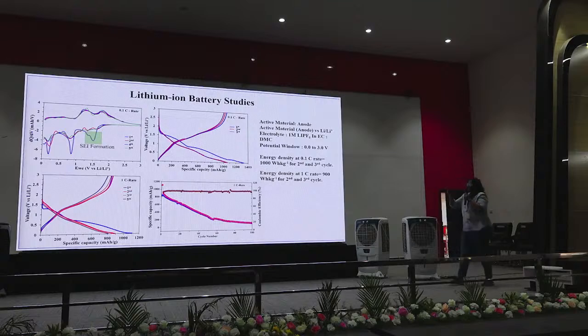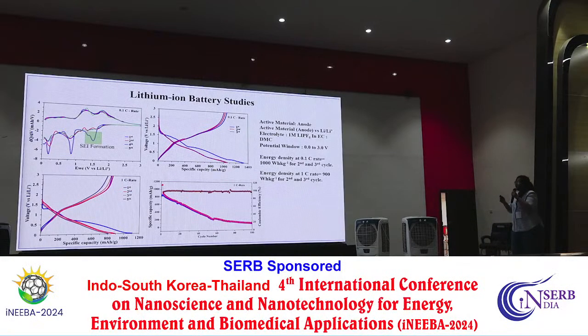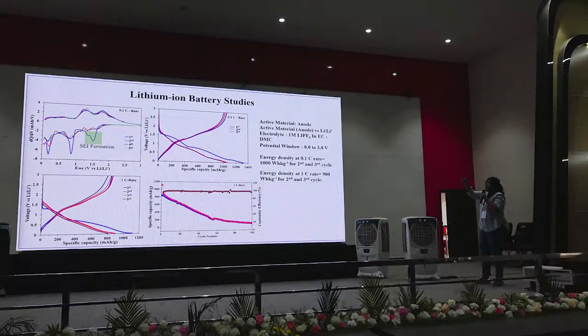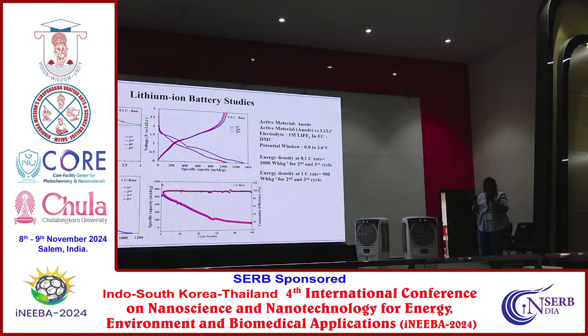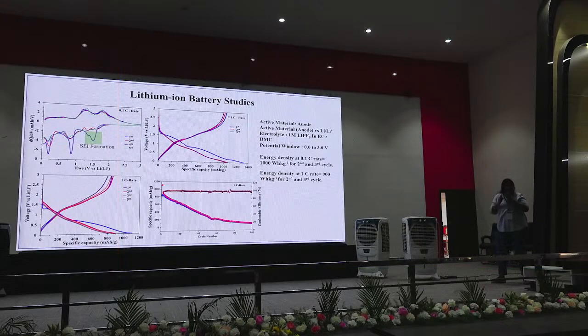This is the dQ by dV graph. The second graph is the charge discharge cycle. Here I have given you all at 0.1 C rate, so the first, second and third cycles. The discharge capacity is found to be around 1300 milliamp hour per gram, and the charge capacity is around 1100 milliamp hour per gram. So there is not much difference in the charge and discharge capacity.